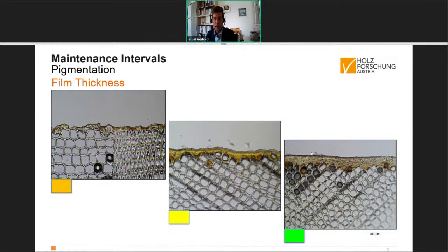The second very important factor for durability is film thickness. You know that there are different categories of film thickness, from non-film forming, low build coating systems on wood like this one, where the coating film is not continuous on the surface, it's interrupted many times, it's not a closed coating film. Then there is a category of medium build coatings with dry film thicknesses around 20 to 60 micrometers. And then there's the category of high build coating systems.